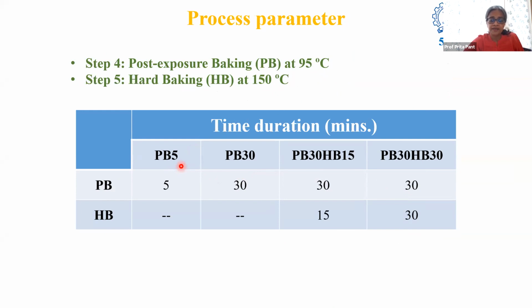So post-bake for 5 minutes, for 30 minutes. In some cases, the post-bake for 30 minutes followed by hard bake for 15 minutes, and post-bake for 30 minutes followed by hard bake for 30 minutes. This is expected to be the most cross-linked sample. This is expected to be the least cross-linked sample.